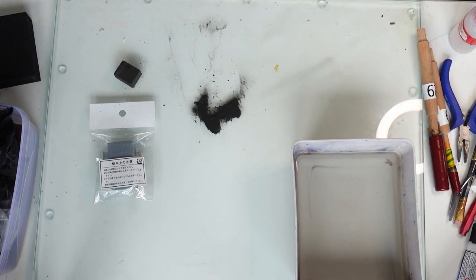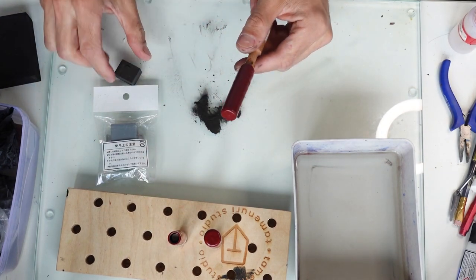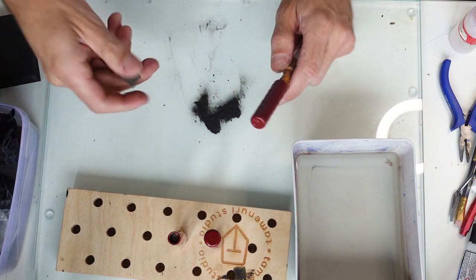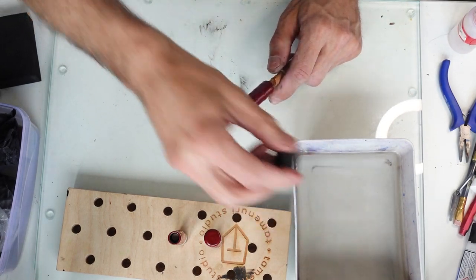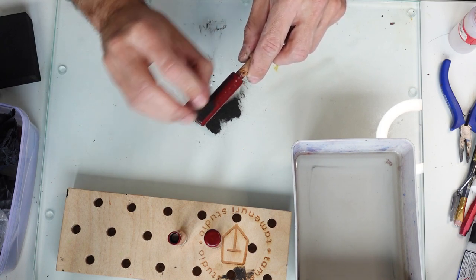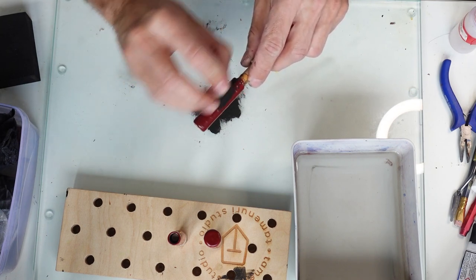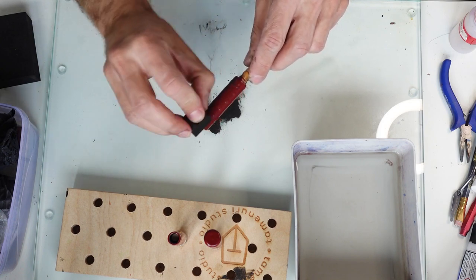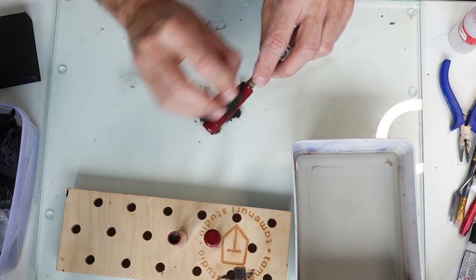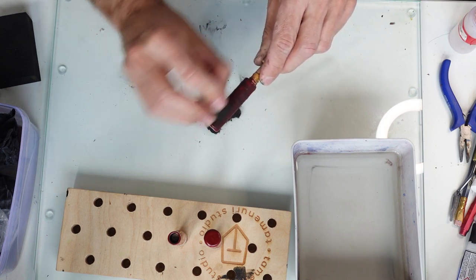Okay, so now we have a cured pen, fully cured pen, and a pen which was later covered with numerous layers of urushi and gold. So I used several colors of urushi and gold pigment, gold powder. And I will use a whetstone for sanding it, because the surface is not even, it's not smooth. Places I showed on the presentation, they are sticking out of the surface. So to sand it with the sandpaper, I would have to glue it on some flat surface, not to sand through the background. I just want to sand to the layer I planned as a background.